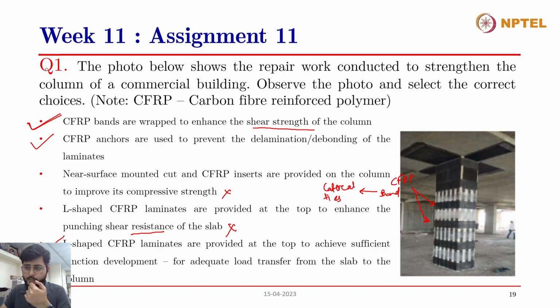Yes, we can see over here also there is anchoring, even if it is not clearly visible in the picture. Basically, the CFRP laminates have wires coming out at the end, and as we have seen in previous lectures, they can be anchored by spreading out these wires on the concrete surface and then applying a coat over it, so that will allow for the anchoring. So yes, CFRP anchors are used to prevent delamination or debonding.